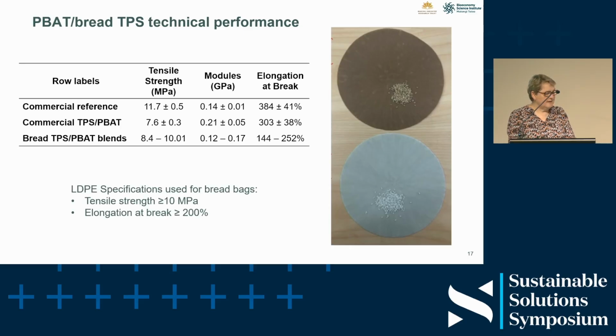But when you compare it with the low density polyethylene material that current bread bags are blown from today, you'll see that the bread thermoplastic starch PBAT blend actually fitted within the range where you want a tensile strength of at least 10 megapascals and an elongation of no less than 200%. So in other words, in theory, we've got a material that bread bags can be made from.